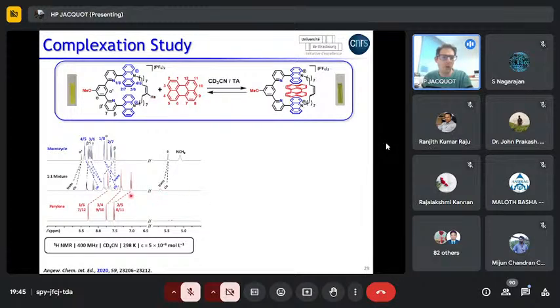So for the one-to-one mixture of host and guest, you have upfield shifts of most of the protons in comparison to the isolated components. So this means that you have some pi-pi stacking interactions, except for the O prime proton, which is downfield shifted. And O prime is inside the cavity of the macrocycle, meaning that the guest goes inside the cavity of the receptor. Also, during this experiment, we observed a color change. So the macrocycle is yellow, perylene is slightly yellow in solution as well. And when you do the one-to-one mixture, you have a greenish color.